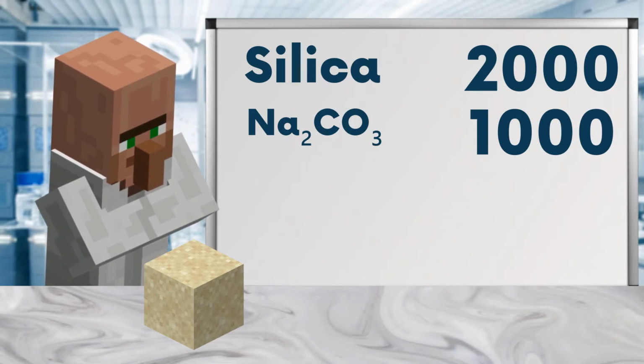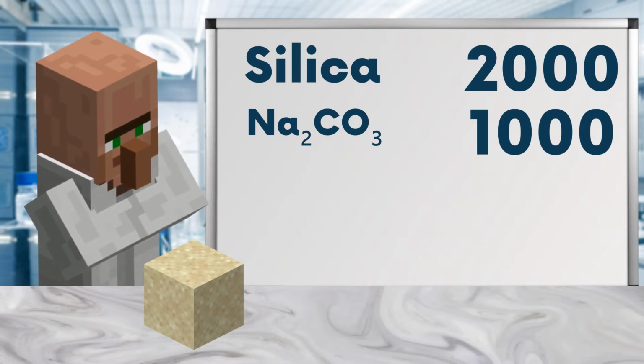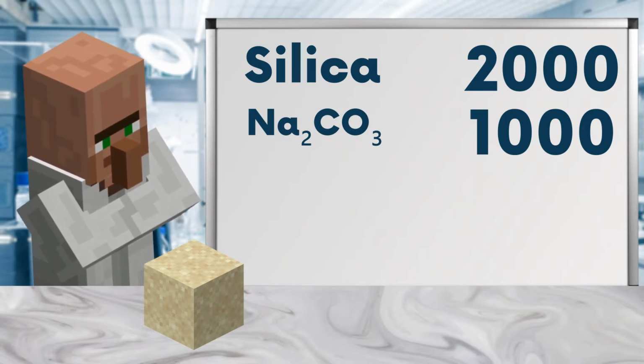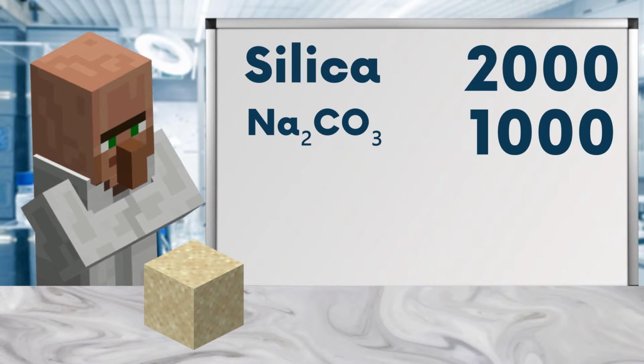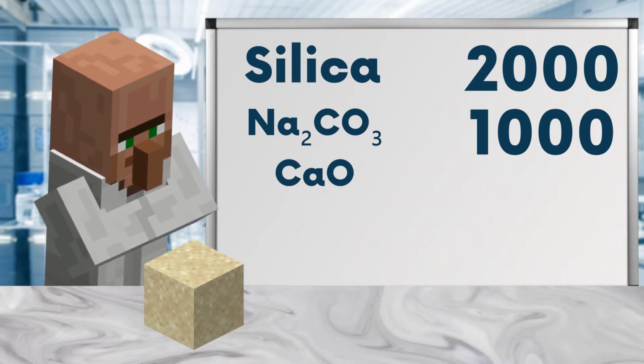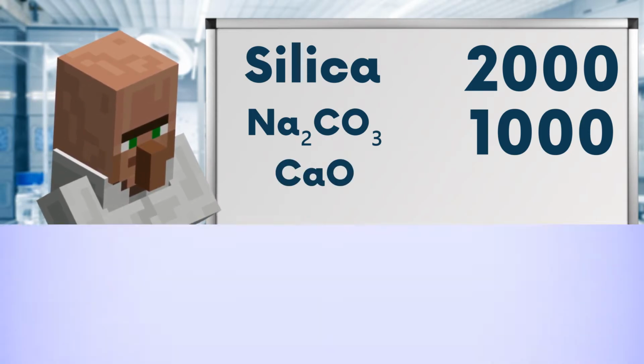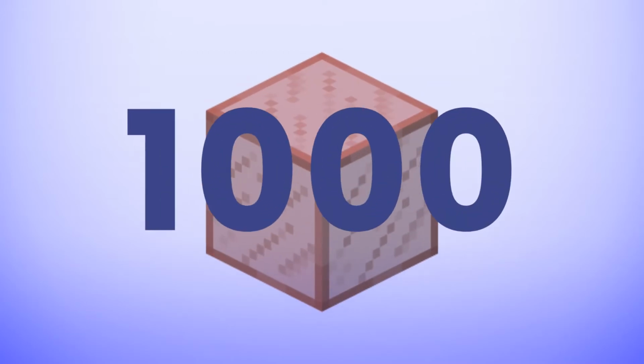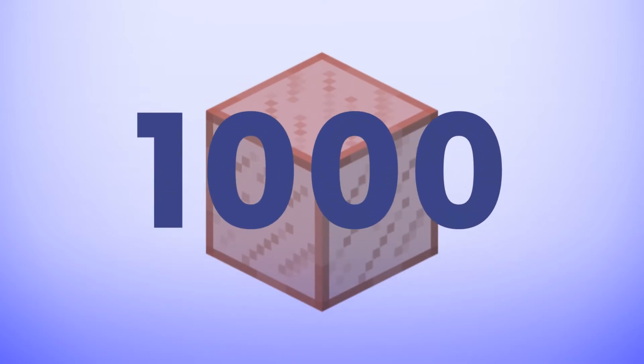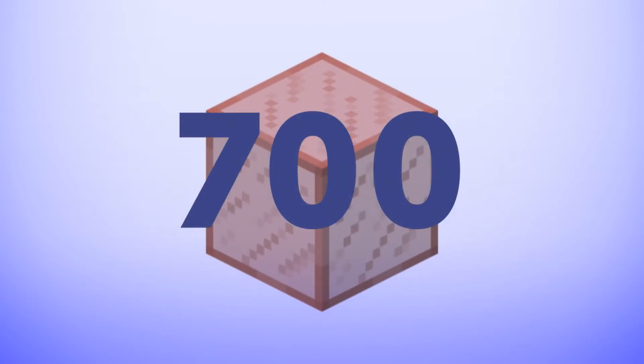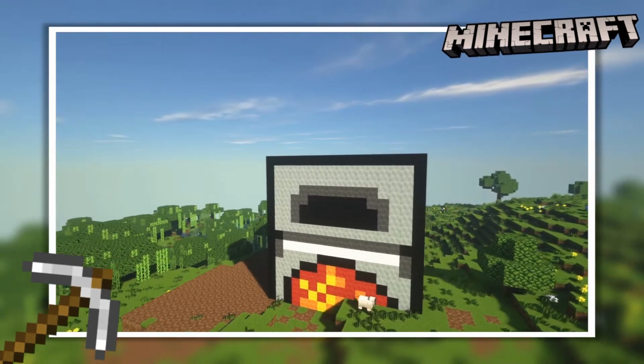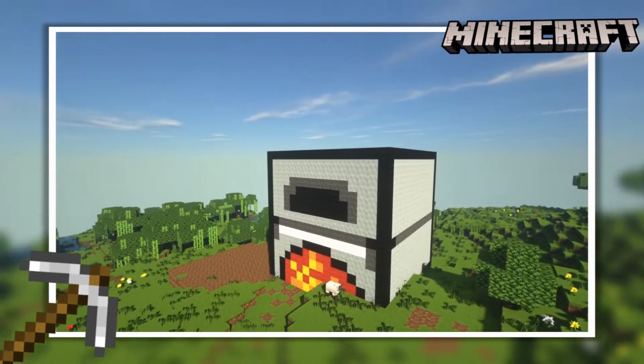But this soda is problematic as it makes the glass soluble, and that's not going to keep your Minecraft build safe from the rain. This can thankfully be fixed by adding in lime or calcium oxide, which restores the insolubility of the glass. This results in a glass that melts at 1000 degrees but can be worked with and formed in temperatures as low as 700 degrees Celsius, which is much more useful for building. This makes our Minecraft furnace more than capable of making glass panes and blocks.